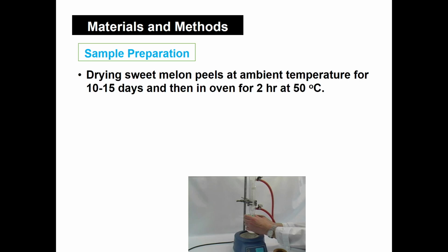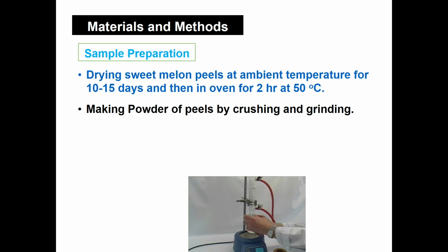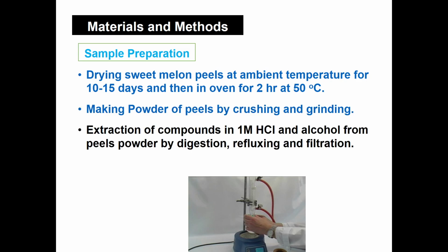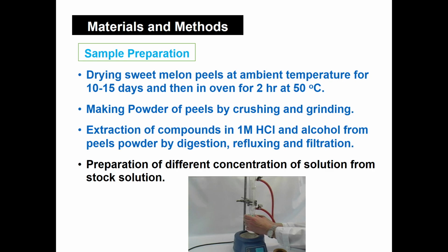In the preparation of the sample, we use simple steps. We dry the sweet melon peels at ambient temperature for around 10 to 15 days in the open environment, and it was summer, so it became dry very quickly, and then we put it in the oven at around 50 degrees centigrade for 2 hours. Then we crush it, grind it, make the powder, and then the extraction process was done in 1 M HCl and alcohol from the peel powder by utilizing the digestion, refluxing, and filtration technique. After preparation, we use this solution to make different concentrations to utilize in the testing of the inhibitor.